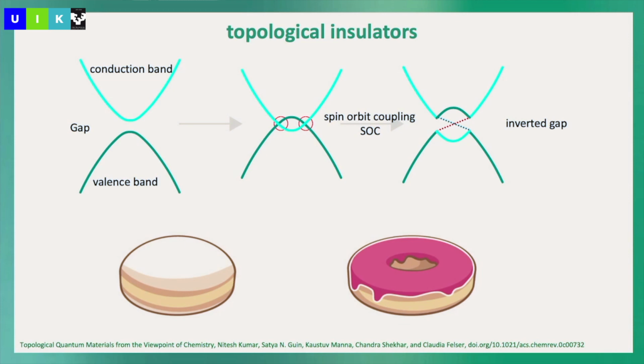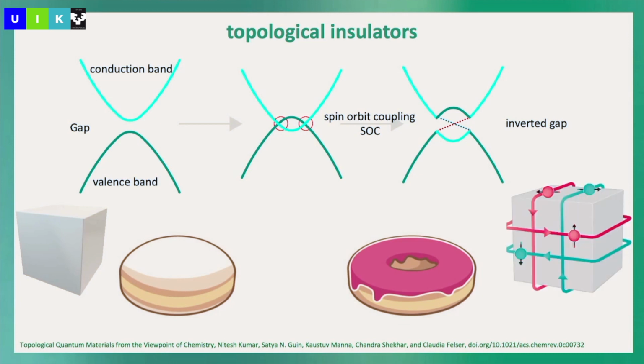Charlie already discussed the edge states. So they are topologically distinguished in the electronic structure, like we see here, the donut and the pancake. Okay. So, and this means that here we have a crystal. If you have a crystal, I grow my single crystals, and this is what I do. Okay, so the crystal is really an insulator or semiconductor, and here we have these interesting spin polarized surface states where the spin and the momentum are locked on the surface of the material.